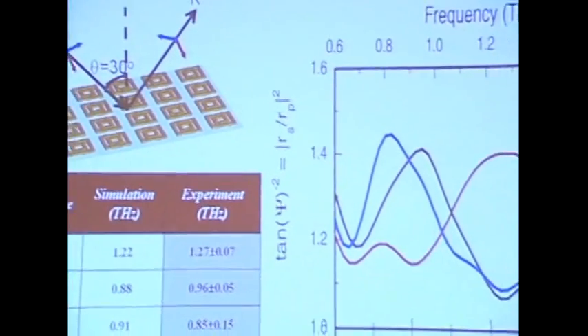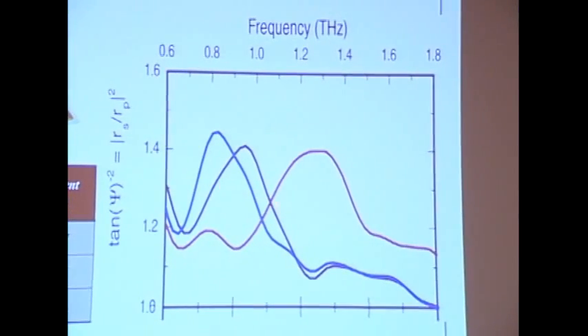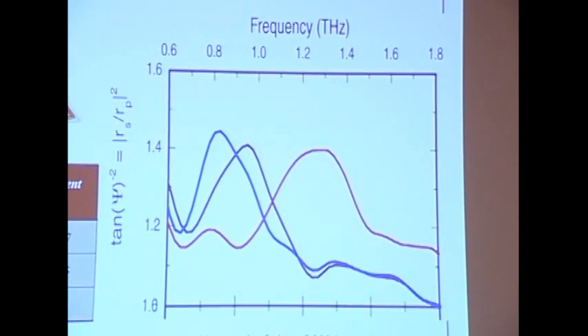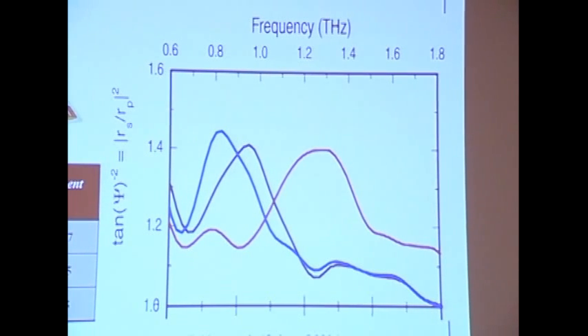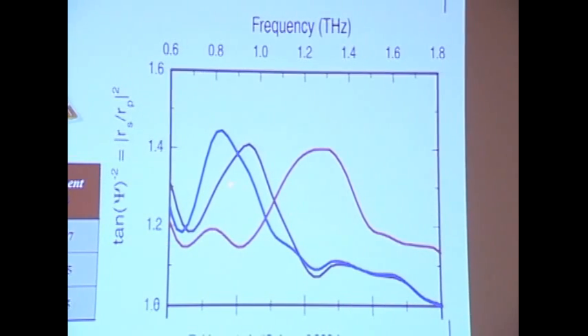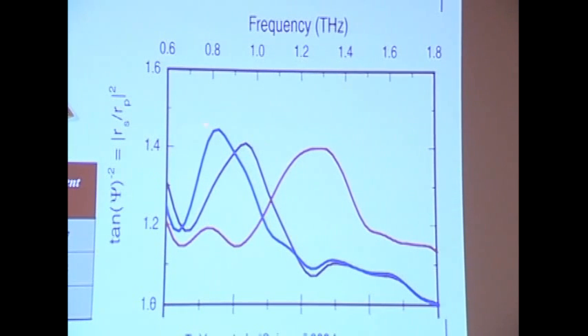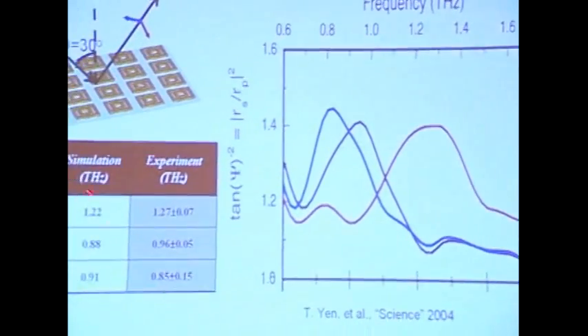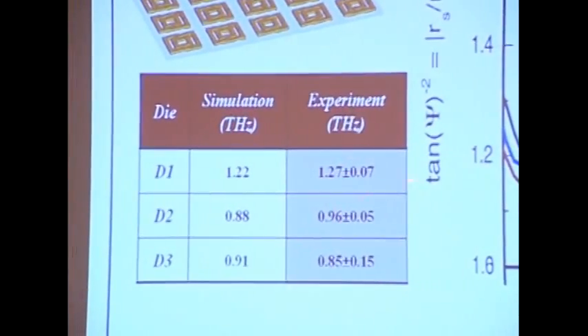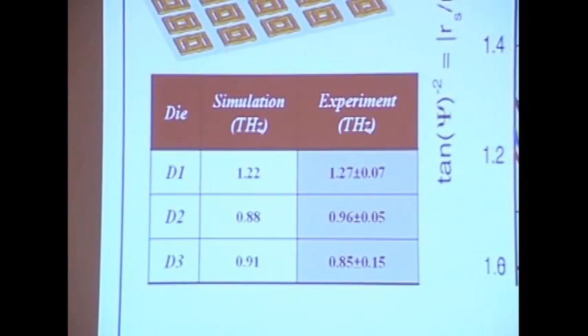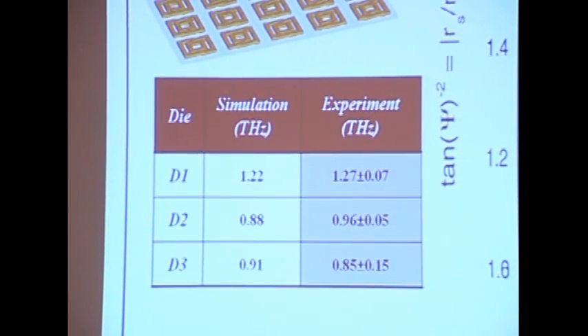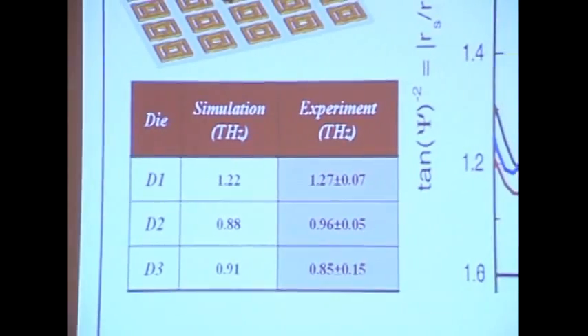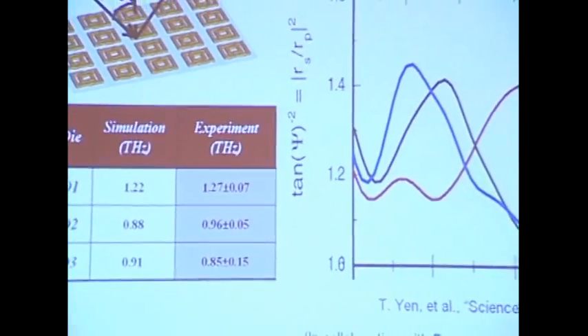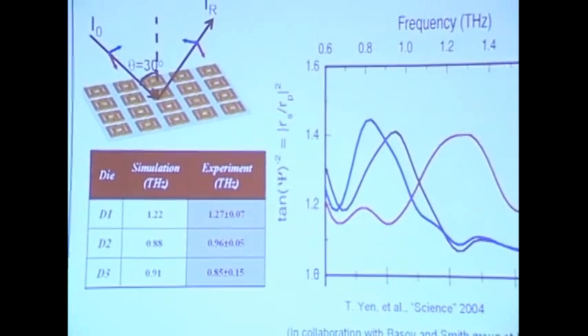So these are the 3 samples corresponding to 3 different frequencies, essentially 3 different sizes. By changing the size of the ring, you can tune the resonance frequency. That gives you a resonance at below 1 terahertz or a little above a terahertz. So this is tunable with the size. This is our simulation result predicting the peak of the resonance versus the experimental result, which agree pretty well. This is in collaboration with the UCSD Basov and Smith group. We believe this is the first artificial magnetic response at far infrared demonstrated.